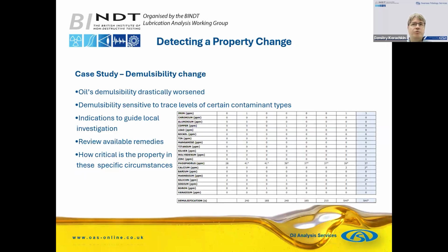Another example of detecting contamination through a property change, we had an oil sample where after a long time of good demulsibility performance, we had a sample with poor demulsibility. So instead of demulsifying after 210 seconds, after 1200 seconds, there was still only 5 milliliters of oil separated. We repeated with a follow-up sample just to make sure there were no issues. And the result held. And one of the things we noticed was very low levels of calcium and silicon in the system. And the demulsibility of oil is a property that can be sensitive to very low concentrations of certain contaminants. So this information gives the customer a chance to investigate, find out where the contamination may be coming from.